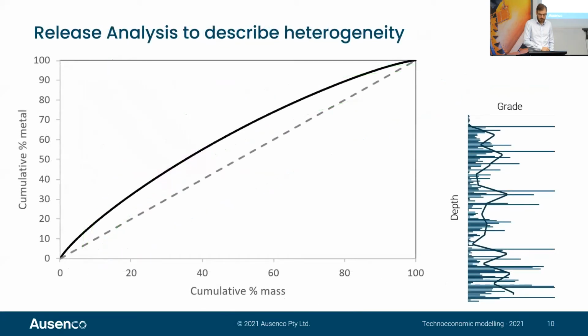So if we look at that initial assessment that I've got on the right there, you can actually plot that. You can take the standard approach where you average over the 10 meters, and then you take into account what would actually be occurring over those 1 meter intervals, and you can get that release analysis that describes the in situ ore heterogeneity. Then you're able to apply some mixing that's occurring due to the mining method and the materials handling that happens downstream, and get an idea of what grade variability that sensor's going to see.